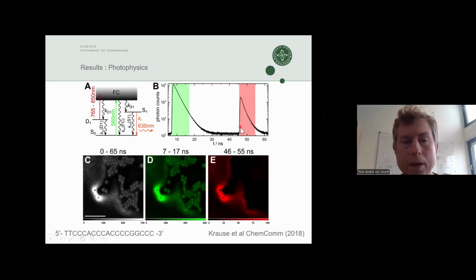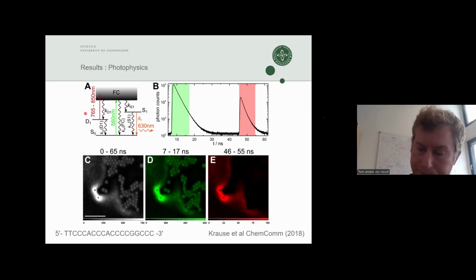As you can see here, by using near-infrared light, we can optically pump the molecule back from the dark state to the emissive state, and we can have what's called optically activated delayed fluorescence. So we can optically activate the molecule from this dark state back to the emissive state. That would be a nice imaging approach to create background-free images, because in this particular case, the fluorescence is anti-Stokes. It's higher in energy than the readout laser. And that would allow you, for example, to make nice background-free images.